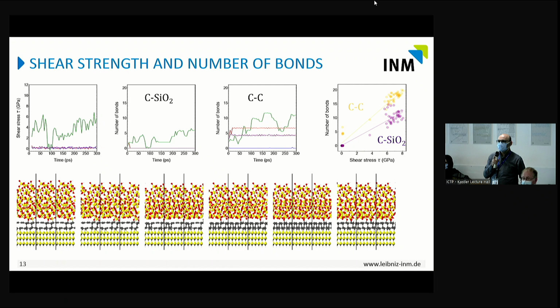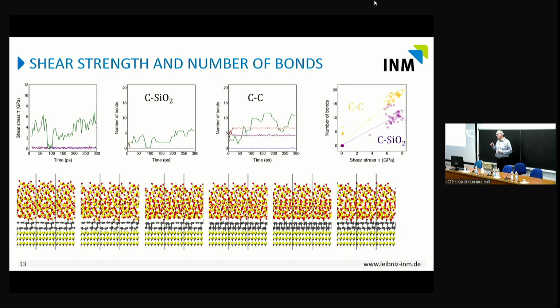In the simulation, in experiment, there's a controlled temperature. And we have done the same simulations at higher temperatures, and actually the whole thing happens a little earlier, but the qualitative behavior is the same. And in AFM, I don't believe there's a big increase in temperature because it's just such a well-conducting system, and it's only these tiny nanometers. So within reasonable timescales, it's probably...